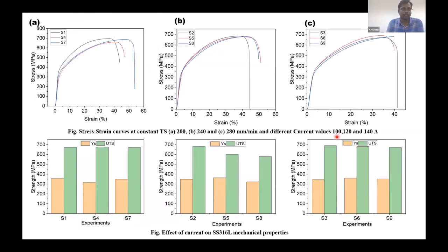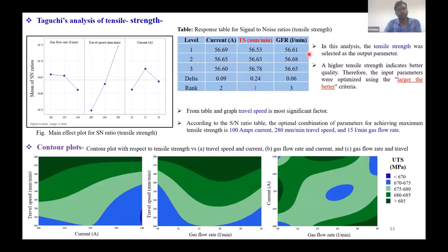So these are some of the results for the tensile, where we are comparing different conditions in order to understand the ductility parameter, or the percentage elongation, that we are having for different cases. And we have observed that at higher current deposition conditions, which we have shown as S7, S8 and S9, we are having more ductility compared to the other conditions. And we have also done some kind of